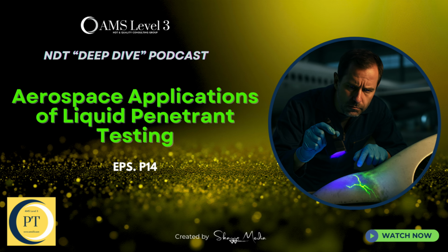Another example cited was inspecting stainless steel welds for the LOFT reactor fuel modules. Why developer-less there? The LOFT reactor was highly instrumented. The challenge was that applying developer spray would contaminate the incredibly intricate areas between the instrumentation leads. It would have been a nightmare to clean. So by using a high-sensitivity fluorescent liquid penetrant without developer, they solved the contamination problem while maintaining detection capability.